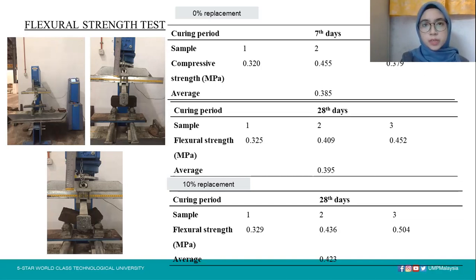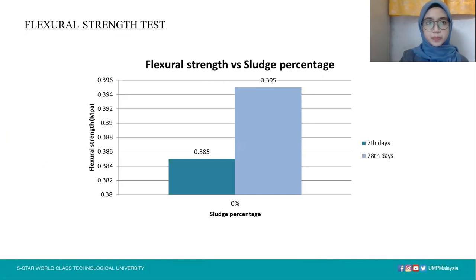For the 7 day, the 10% replacement cannot be taken because we cannot enter the lab due to the MCO problem. Now we proceed to the flexural strength test chart, which we can see here. This is for the 0%. The flexural strength increased from 7 day to the 28th day. For 7 day is 0.385 megapascal, and for the 28 days, 0.395 megapascal.